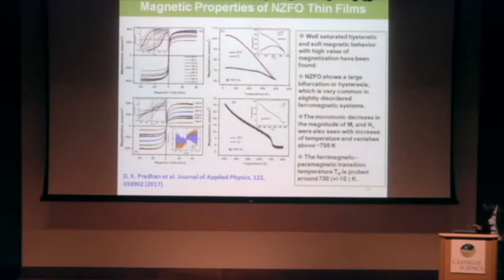Then we have studied some magnetic properties of the composite thin films. Before that, we studied the magnetic properties of nickel zinc iron oxide thin films. Here, this is the low temperature MH loop from 20 Kelvin to 395 Kelvin, and this is the expanded core at low temperature. Here we observe a large bifurcation, which indicates a slightly disordered type ferromagnetic system. And as the temperature increases, the magnetization decreases.